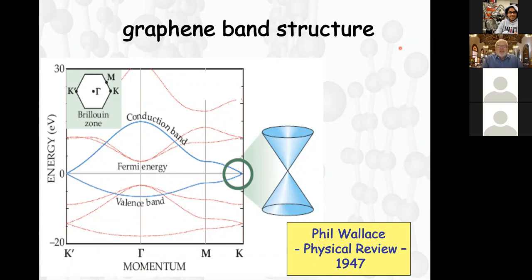So I'm coming back here and again showing you this band structure. This is for graphene, energy versus momentum. The low energy states are these blue pi bands, which are odd under inversion in a graphene sheet. And my little circle reminds you once again that the low energy states are close together in momentum space. And that means that if you have some part of the Hamiltonian which varies slowly in space, then it just produces an effective potential that has the periodicity of the pattern of the interlayer coordination and is not sensitive to microscopic physics. Actually, in these Moiré systems at a general twist angle, they're not really two-dimensional crystals if you look at the position of every atom. But the point is that for low energy properties, that simply doesn't matter.